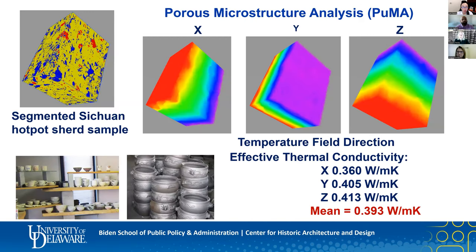If we assume that potters figured out through trial and error what raw materials, processing and fabrication methods, and firing regimes would result in the products that work the best for certain uses, then regarding porosity, we can think, what does a cooking pot need? And actually it needs a good amount of porosity so that the non-clay particles can expand and contract on a cooking fire without the vessel cracking. And large connected pores will help retain heat in the vessel.